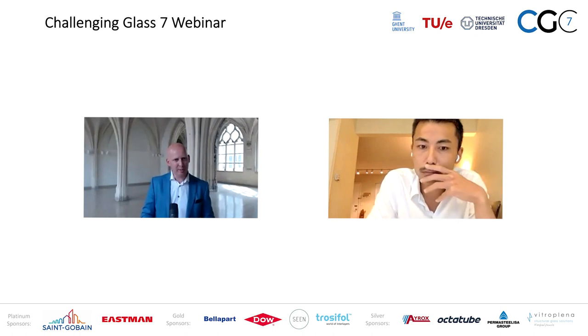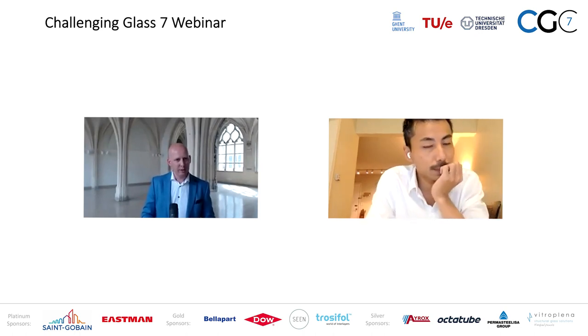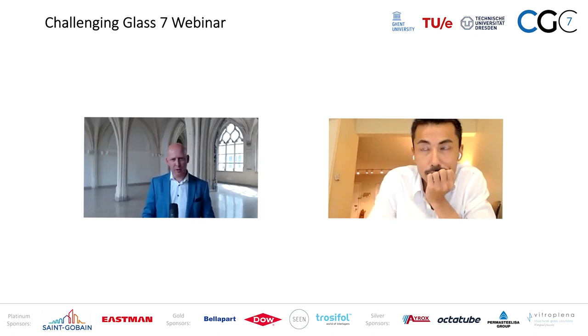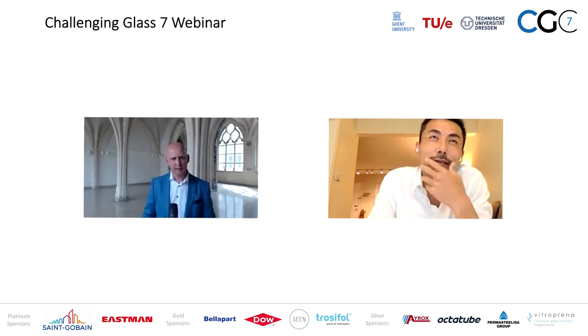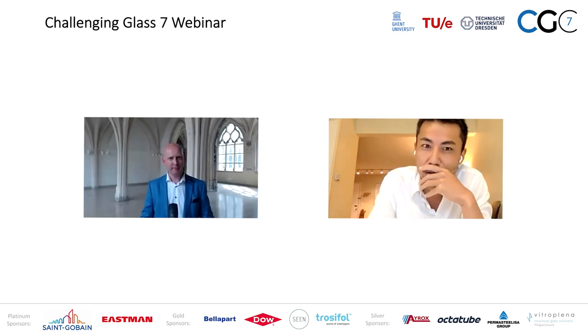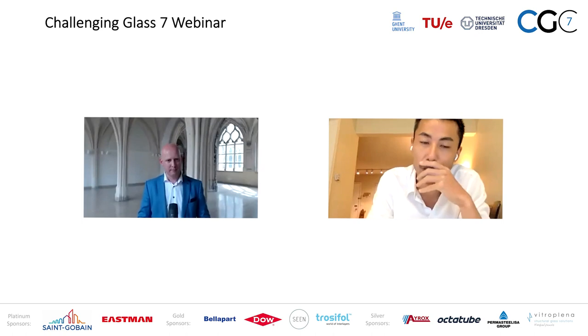Then we have received some questions about the column that you showed. First question from Jan Belis here from the floor. When you compose these glass columns and you stack them together, the independent pieces, how do you then avoid contact stresses or high peak stresses between those panels or between those pieces? Yes, there's close to 1 millimeter thick silicone adhesive that was meant to bond two glass together, but then we wanted to keep it modular. So we ended up applying it on one layer and let it cure so that it remains somewhat ductile. So that added a dampening layer to avoid this contact stress.